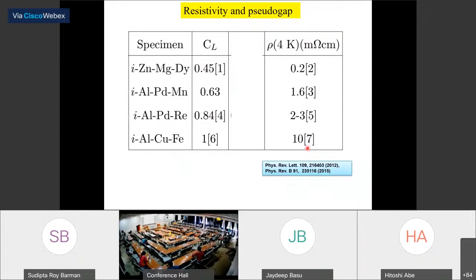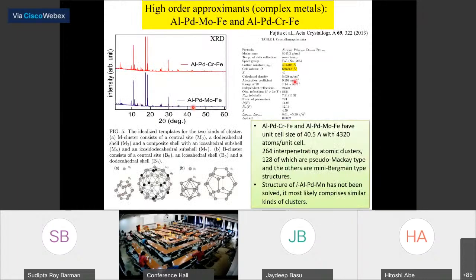So the high order approximants, which I wrote in the title as complex metals, what we studied are Al-Pd-Mo-Fe and Al-Pd-Cr-Fe. So this is their XRD pattern. They look very similar, so they are isostructural. And the group who made these systems, for the first time, determined their structure. As you can see, it has a lattice constant of 40 angstroms, and it has 4,320 atoms in the unit cell. And these also comprise these kinds of clusters, like in quasicrystals, where you have clusters which form their structures.